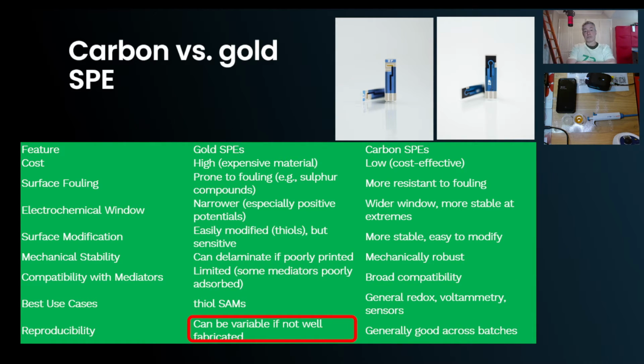This statement here that gold can be variable, it's true that gold can be variable, but carbon can also be variable. It's really about your manufacturing, and it's something that we really lean upon. Now, there's an economics here, because at ZP we promote carbon over gold because it leads to a low cost sensor, a low cost assay. That means more people buy carbon from us, which means we're making higher volumes of carbon versus gold. And the more you manufacture something, the more regularly you do it, it impacts on the quality. So in our particular case, I would argue that carbon electrodes, because of their higher volume, which is driven by the lower pricing, lead to a higher quality per electrode.